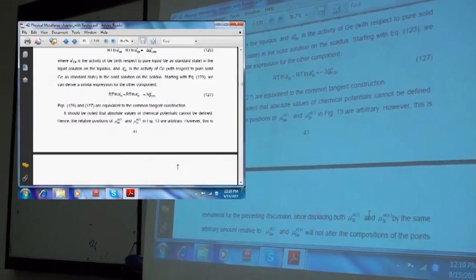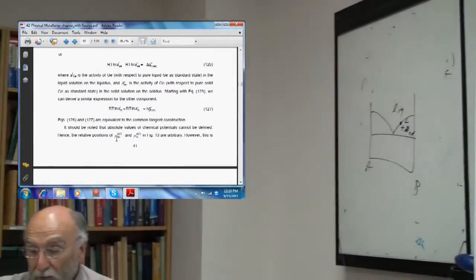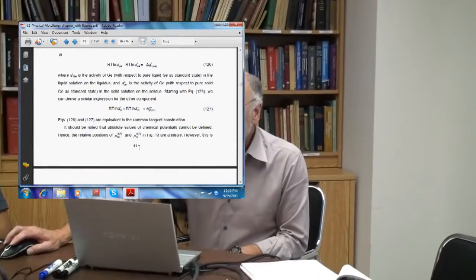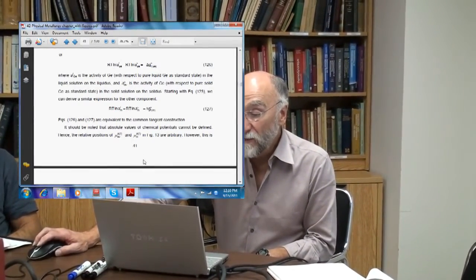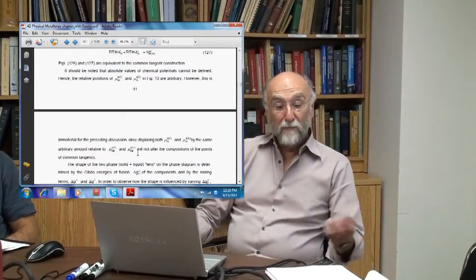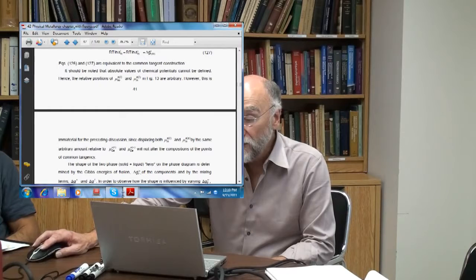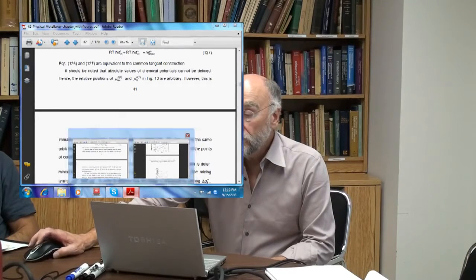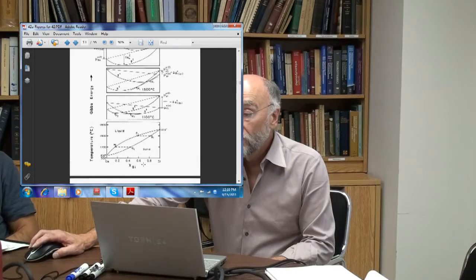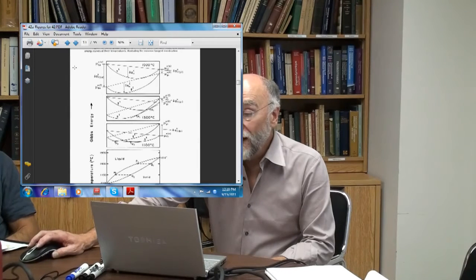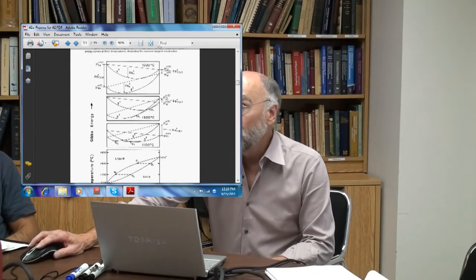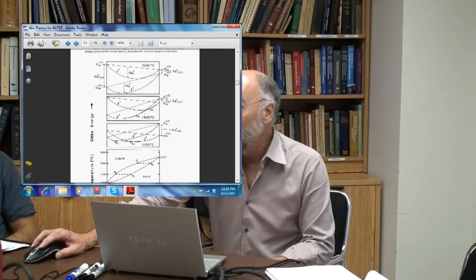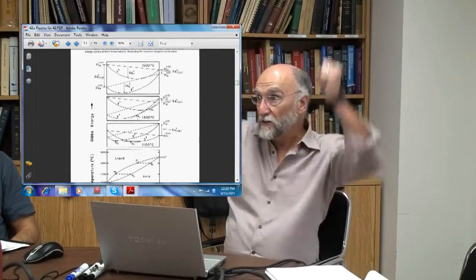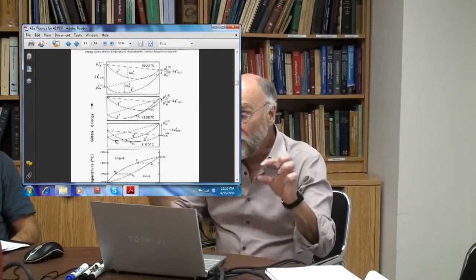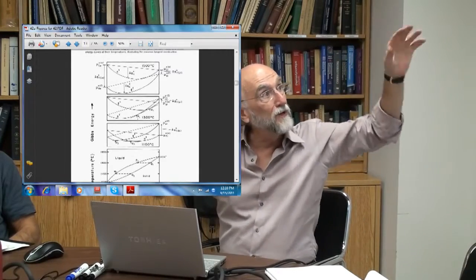Let's talk a little bit about the standard states. Notice the relative positions of the chemical potentials are completely arbitrary. The mu naught liquid and mu naught solid are arbitrary. This is immaterial for the preceding discussion, so you can take the curves here. It doesn't matter what the relative value is. I could take both these points here, raise this point by 1,000,000 joules, raise that point by 1,000,000 joules. It would not change the position of the points of tangency. You're just making a linear shift of the curves. As long as you keep the distances between them the same, the endpoints don't really matter.